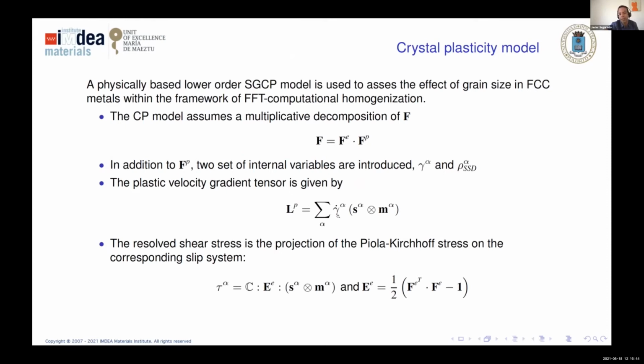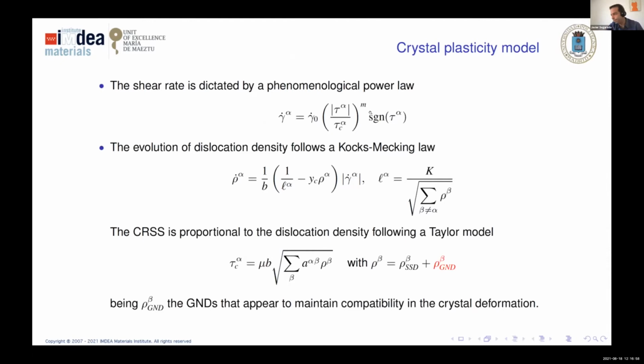The plastic velocity gradient is the Schmid tensor multiplied by some shear rates, and the driving force is the resolved shear stress tau, which is nothing but the projection of the stress through the Schmid tensor. The shear rate follows a phenomenological power law, where the driving force is the resolved shear stress. Because we want to limit the number of parameters very much, we use a very simple, physically based model.